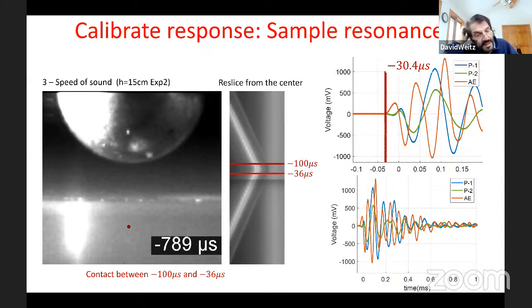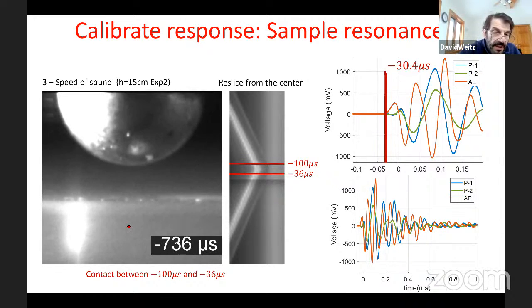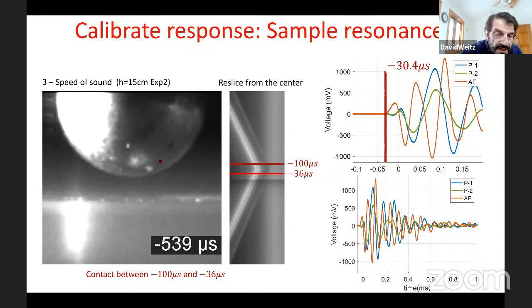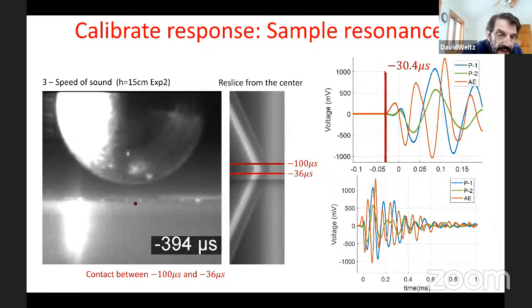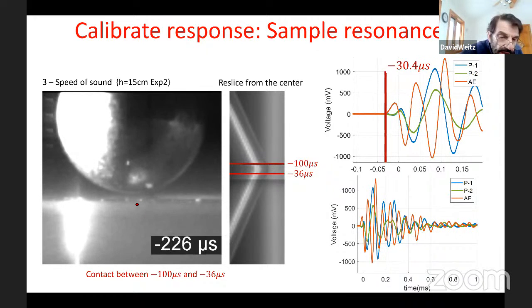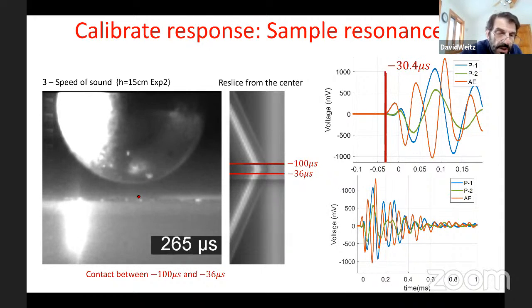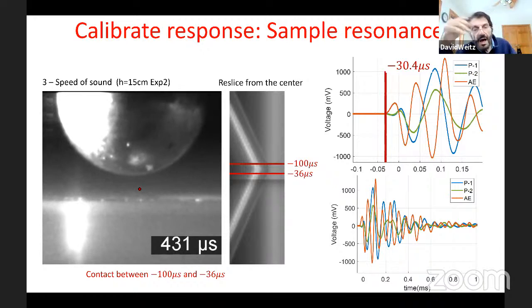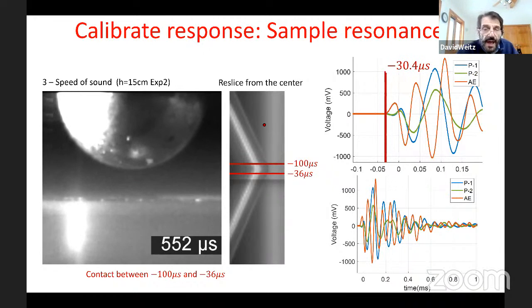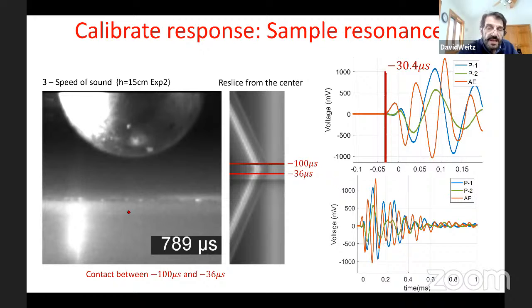We take advantage of the camera, and we can actually watch the steel ball falling on the surface. Watch very carefully. This is very, very high speed, and it makes contact right there. And if you watch very closely, you can actually see a little bit of adhesion where it's pulling off. There's a little bit of sticking. And this is a kymogram. We can look at just one of the slices to the center and see how it measures where the impact is.